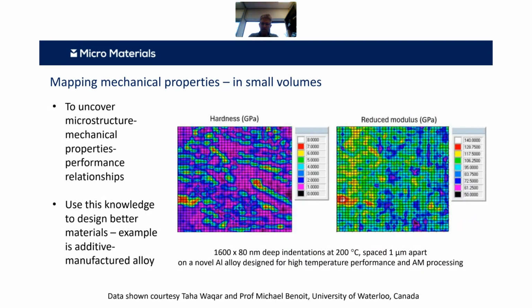So it's another example, in this case of mapping, again, a small volume. This is not a bio application by any stretch. This is a high temperature test map into a novel aluminium alloy design for high temperature performance and additive manufacture processing. And this map and things like this are designed to uncover these microstructure, mechanical properties, performance relationships at high temperature, and then to use that to design better performing additive manufactured alloys for these applications.